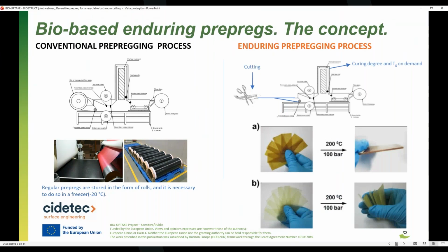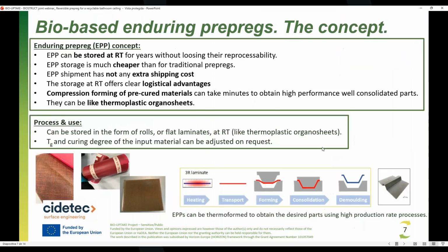composition. Unlike this, so in the image above, we see the enduring prepreg. I mean, we have different flat laminates. We put them together, and with pressure and temperature, we obtain a multi-layer material. But if we do so with a common regular prepreg, we don't get this adhesion between layers.